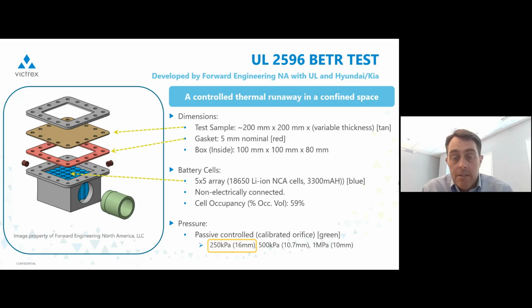This test is typically conducted at a few different pressures. The green cylinder is basically a calibrated orifice that allows for different pressures. We ran this at 250 kPa, and that was what was recommended to us by Forward Engineering as the most applicable to the environments and the arrangements that these materials might see in a lithium-ion battery. Next one.